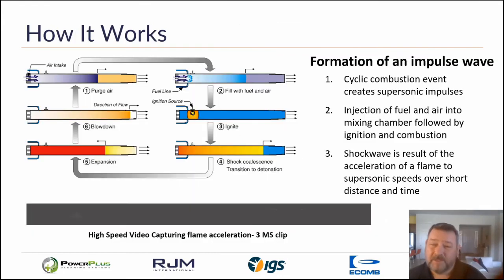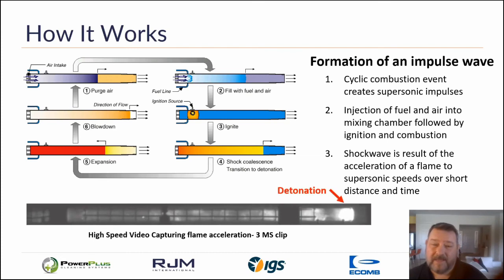Our approach to pulse detonation cleaning is very simple. It is essentially an engine that was adapted from the GE propulsion side. We are mixing gas and air in a combustion tube and igniting it, and we're not storing the pressure, we're not pre-compressing the gases. Everything is done as it passes by the ignition, and this allows us to run a series of rapid impulses very effectively. It is that piling of impulses, usually between 20 to 30 impulses, that creates a massive amount of cleaning energy and competing pressure vectors that are very effective at dislodging the ash.